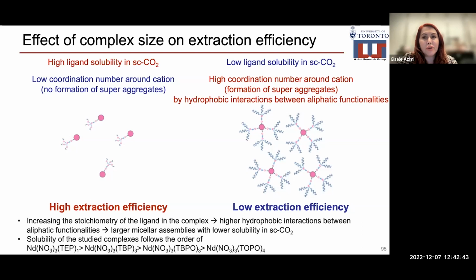On the contrary, low ligand solubility in supercritical CO2 and high coordination number around the cation, which results in the formation of superaggregates by hydrophobic interaction between aliphatic functionalities, results in low extraction efficiency. Increasing the stoichiometry of the ligand in the complex results in higher hydrophobic interactions between aliphatic functionalities. So we have larger micellar assemblies that have lower solubility in supercritical CO2. The solubilities are as follows.